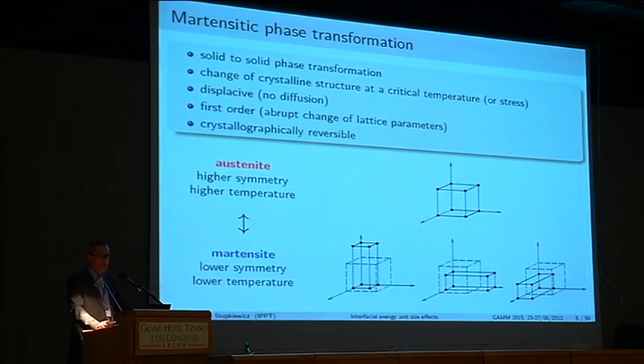Okay, so a bit more about the martensitic phase transformation. It's a solid-to-solid phase transformation, and it exhibits a change of crystalline structure at a critical temperature or stress. The transformation can be induced either by temperature or by stress, so that at high temperature, we have an austenitic phase, which has a higher symmetry, and it's stable at higher temperature, and then we have martensite, which is a lower symmetry, lower temperature phase. And the transformation is displacive, so there is no diffusion involved, which means that it can occur pretty fast, and as I already said, it's crystallographically reversible.